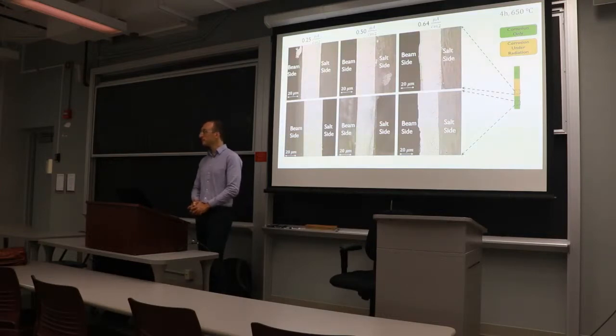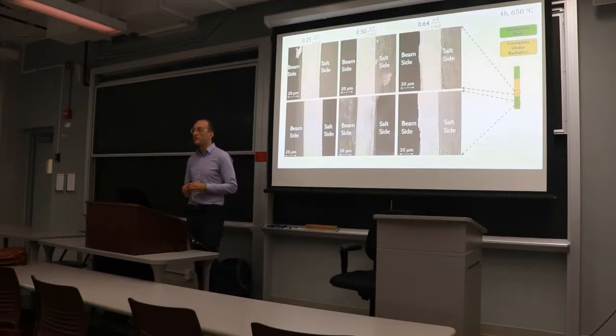So what's the level of dPA or fluence this would be equivalent to, in terms of difference? Good question. This is 100 to 500 times the dPA rate that you'd see in a reactor. So we push the protons in, and we're getting maybe 0.1 dPA. Where in a reactor do you mean? I'm thinking middle of the core, let's say. Middle of the core. Outside the core, it's going to be even worse. When you get fewer neutrons, I expect you're going to get less of a slowdown effect. The big question now is, if we reduce the proton beam current by a factor of 100, will we still see a slowdown? And if we see an acceleration, would there be a slowdown in the neutron case?